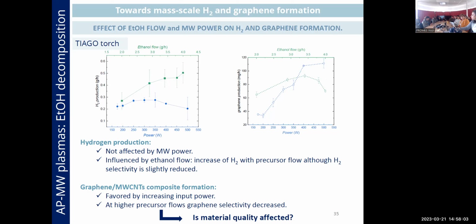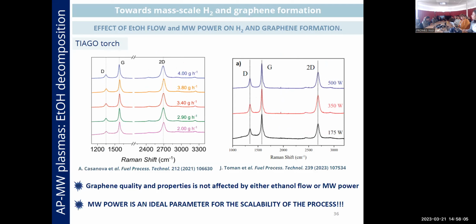What about the quality of the material? In the case of torch discharges, graphene formed by the decomposition of ethanol is not affected, neither by modifying the ethanol amount nor by changing the input parameters. So it can be suggested that microwave power is an ideal parameter for the scalability of the process, since we are increasing the production but keeping the qualities of the materials.